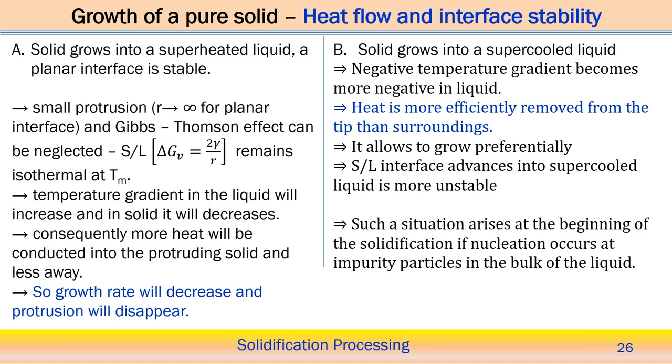If you remember, when we tried to understand the interface during the solidification process, we said the curvature effect is taken care of by the Gibbs-Thomson effect. So since r tends to infinity for a planar interface, the Gibbs-Thomson effect can be neglected in this case. When the curvature effect is neglected, the equilibrium temperature remains exactly at the melting point temperature during this process.